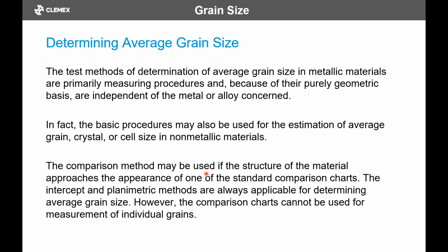Now, to measure grain size, there are various methods, but overall, the idea of measuring grain size is just that we're measuring what we see here, on a purely geometric basis. So that means that we could measure other things than grain size with a grain size method, like the one that we will be talking about. You will see some examples afterward. So what we're saying here is that we can estimate the average grain size, crystal or cell size of non-metallic materials, the same way as we would do for grain size. Generally the approach is to use a comparison method using charts, but we can use the more accurate, if you want, intercept and planimetric methods. And the charts cannot be used with the measurement of individual grains, which is sometimes what we're looking for.